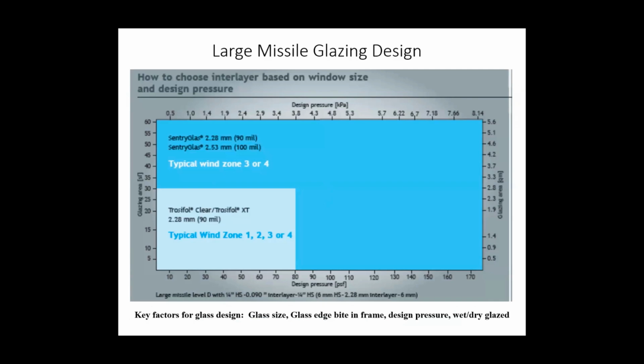So, when to use PVB versus ionoplast. And once again, this is just general guidance. But if your design pressure is 80 PSF or less, and your window size or door size is less than 30 square feet, then PVB should work. When your design pressure is higher or your glass sizes get bigger, that's when you need to consider using the ionoplast, because the PVB will pull out of the frame during the cycling test.